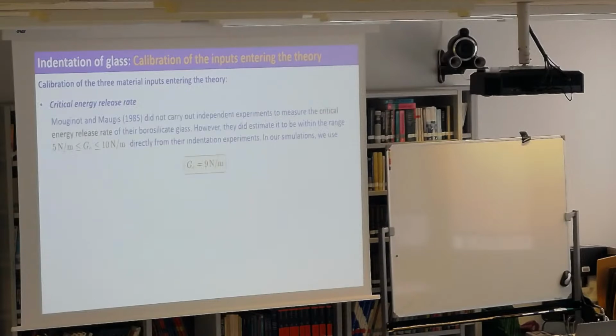Critical energy release rate, they didn't measure directly. From the cone crack, they came up with an estimate which is consistent with other measurements of GC for glass, 9 newtons per meter.